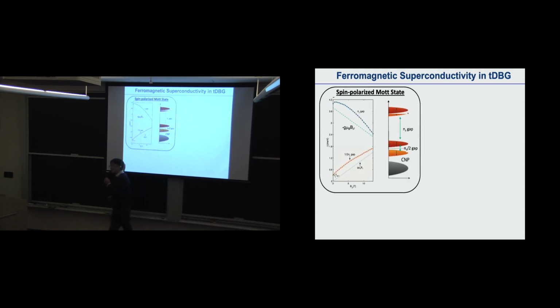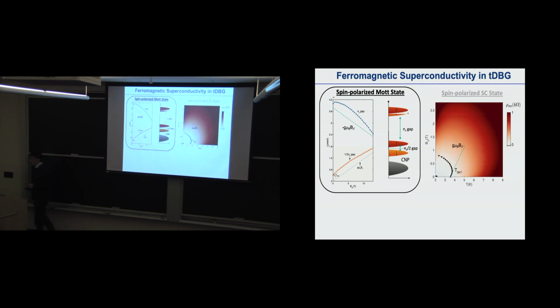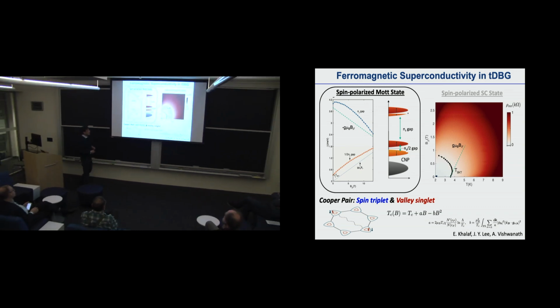What's really happening is basically we believe this is tied with the spin polarized correlated gap, indicating that the Cooper pairs are made out of the same spins in the system. Our collaborator Ashwin's group came up with the simplest argument: like the superfluid helium-3 case, if you think about minority spins and majority spins that constitute the ferromagnetic Mott gap - if you dope this system to create superconductivity, you have two pieces of the Fermi surface with polarizations. Like the helium-3 case, when you apply the in-plane magnetic field coupled with the Zeeman field of the spin, you tend to increase the TC in one of the Fermi surfaces, which will tend to increase the TC in the system.